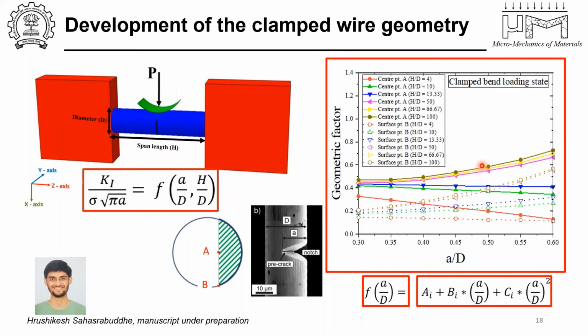But even for the larger aspect ratios, there is a range of crack lengths where the crack can grow stably in these wires. And in these wires, this happens because the cross section that the crack propagates into does not remain constant. As we go from 0.3 to 0.5, in fact, the crack is expanding in area. And then from 0.5 to 1, it is decreasing in area. So that is the reason that you see this kind of scatter or difference.